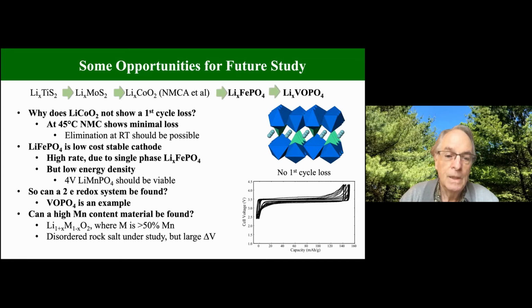But the real issue for us was, is a 2-electron redox system possible? And in particular, can a crystalline lattice withstand 2 lithium ions going in and out of the structure? So we've looked at that, and I won't talk about high manganese content materials. There's a lot of interest there. I understand BASF is actively working on it, and the disordered rock salt is under study. There's a very large voltage change between fully charged and fully discharged.